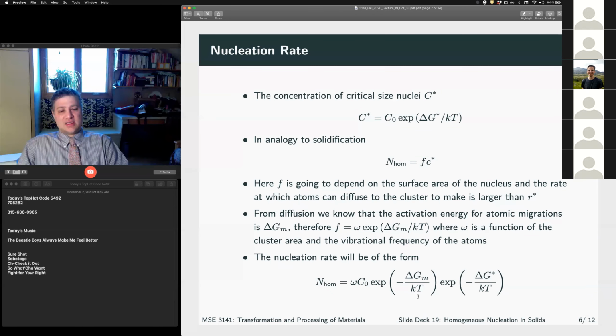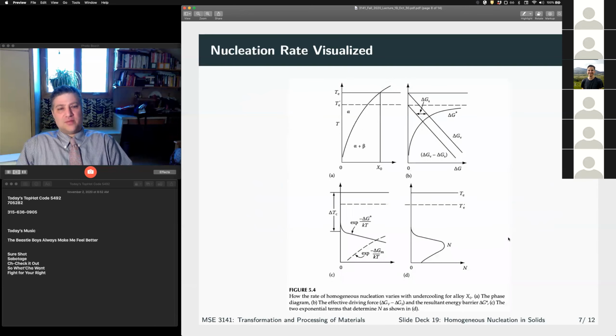The nucleation rate has our delta G star term, like we saw from solidification, but now we also have a diffusion term. How fast can the atoms migrate, right? And it's the combination of these two exponentials that determine our nucleation rate, okay? And to add just another little wrinkle, these can be opposite in sign. Our Gibbs free energy for migration can be different than our Gibbs free energy for nucleation, okay?